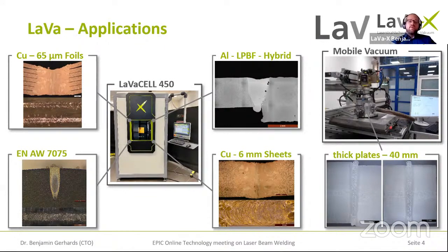Maybe an outlook for our company at the moment is that we can also reach very high penetration depths. As I mentioned before, the possibilities go up to 100 millimeters and more. But it is not very beneficial to build a big vacuum chamber for those high penetration depths, because usually the parts that need high penetration depth are quite huge in dimensions. Therefore, we created a mobile vacuum welding device that generates the vacuum just where it's needed, around the welding where it takes place, and then it moves alongside the welding process.